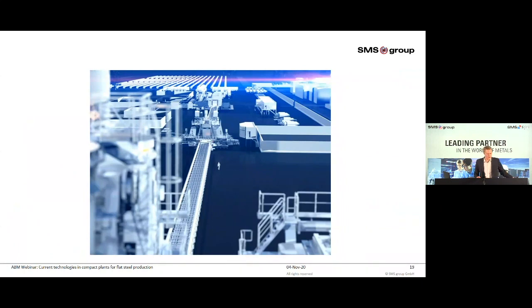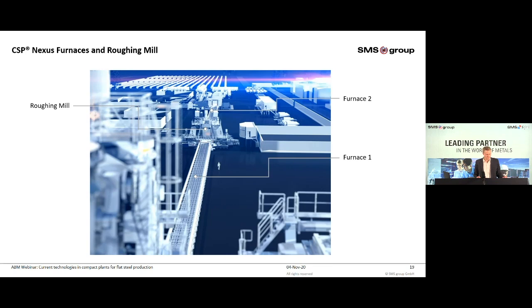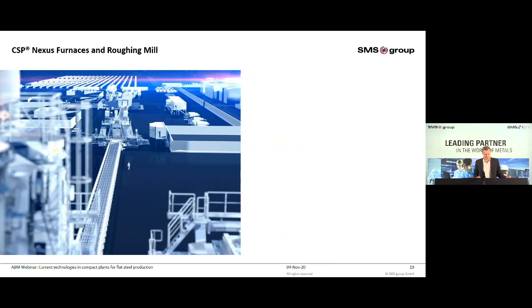Having a look from the caster platform, you can see the first tunnel furnace, the roughing mill, and the second tunnel furnace. The task of tunnel furnace number 1 is to increase the slab temperature, to equalize the slab temperature for a risk-free production of crack-sensitive grades, to enable the batch process, so the slab is cut before beginning the rolling process in the roughing mill, and to enable the work roll change in the finishing mill.